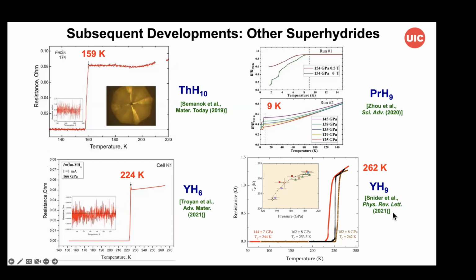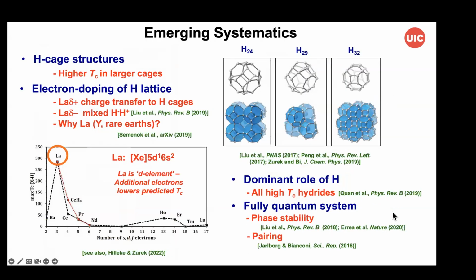So of course, now we have a whole series of binary systems with very high TCs approaching room temperature in thorium, and now yttrium with different stoichiometries, praseodymium, and emerging systematics have come from these studies. A lot of this work has been done by Eva Zurek and her group, looking at all the systematics in these various systems, based largely on theory, but where we can compare with the available experiments. There's fairly good agreement for the binaries. These are electron doped hydrogen lattices, where there's charge transfer from the heavy metal to the sublattice, which consists of these cages, H24, H29, H32 cages, and the systematics that also emerge is that we have the highest TCs for lanthanum and yttrium in these systems, and this fall off in TC with increasing number of f electrons arises from essentially magnetic effects in the system.